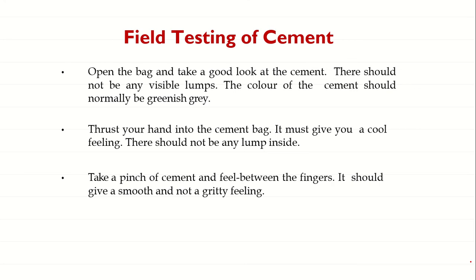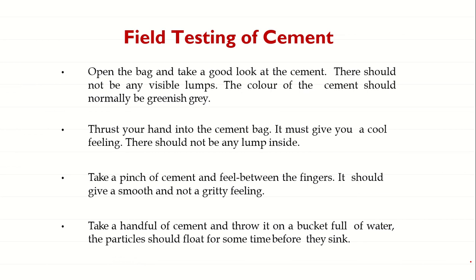Another field test: take a pinch of cement between your fingers and press it. If it gives a very smooth feeling, the cement is good. It should not give you any gritty or rough feeling — if the cement is mixed with impurities, you will get a gritty feeling between your fingers.